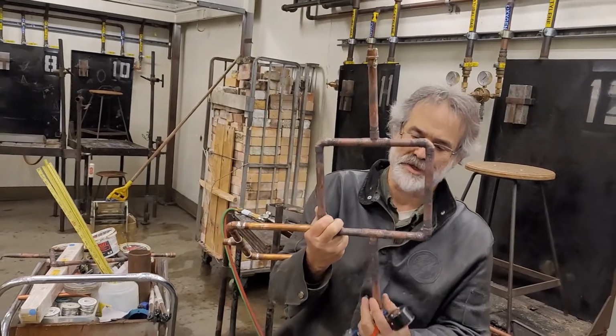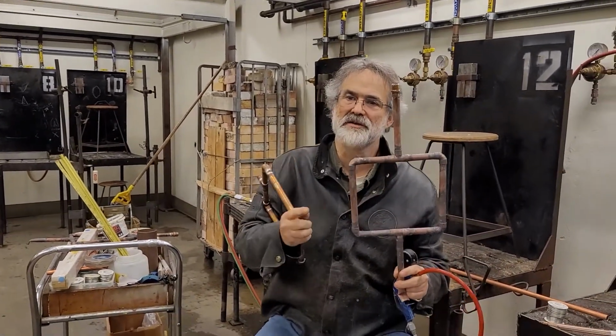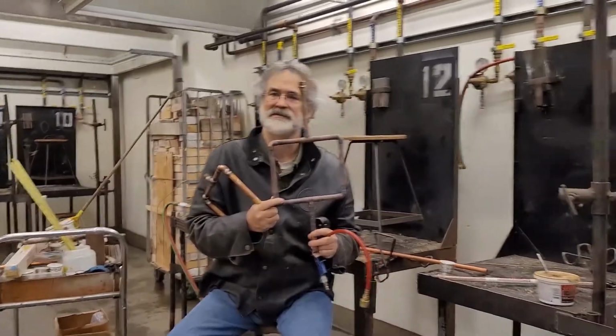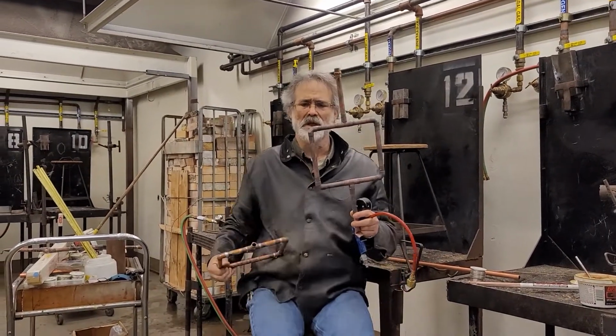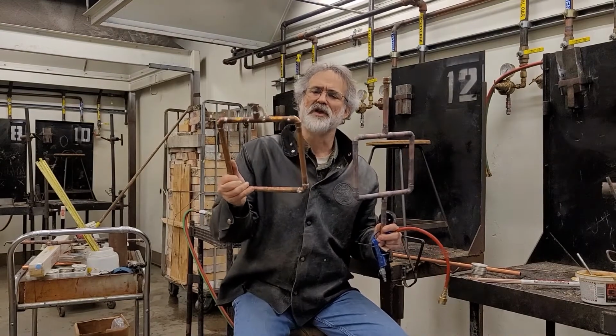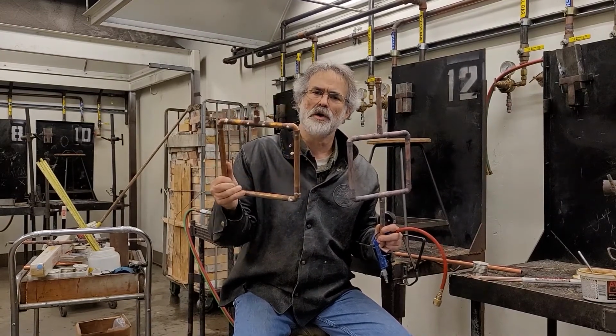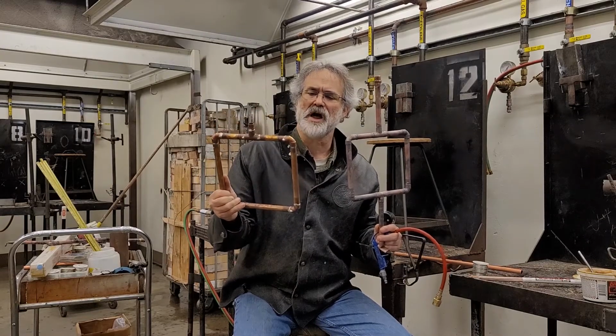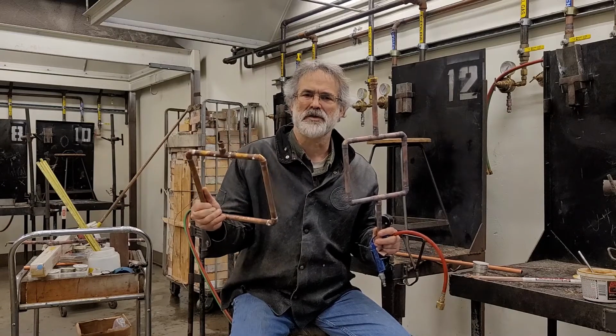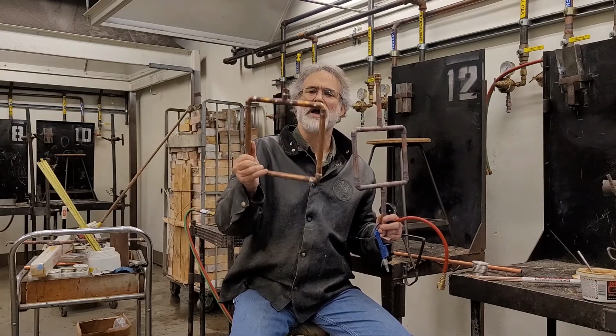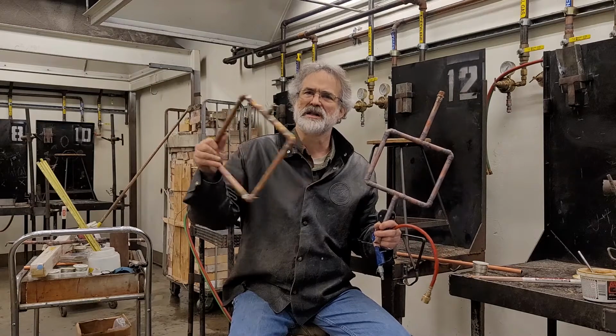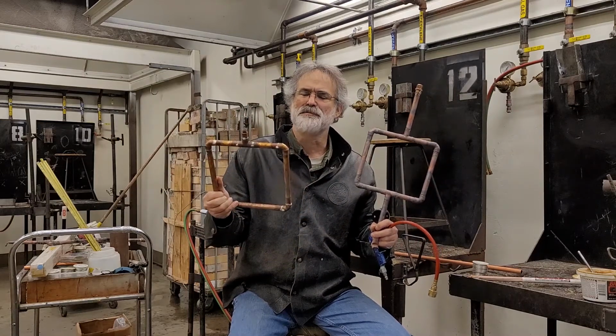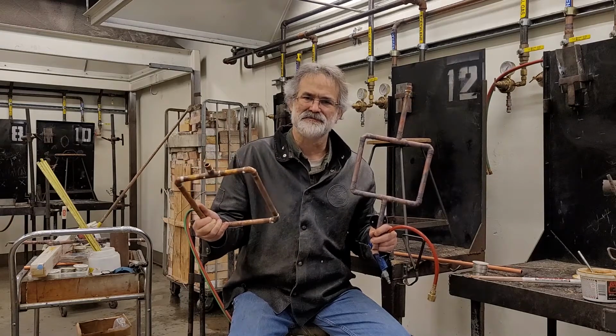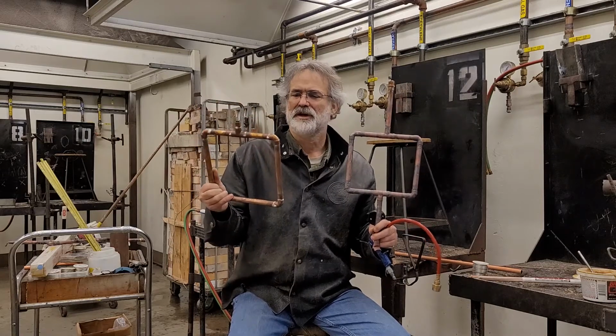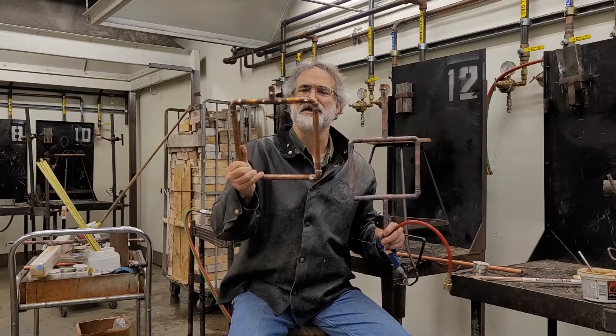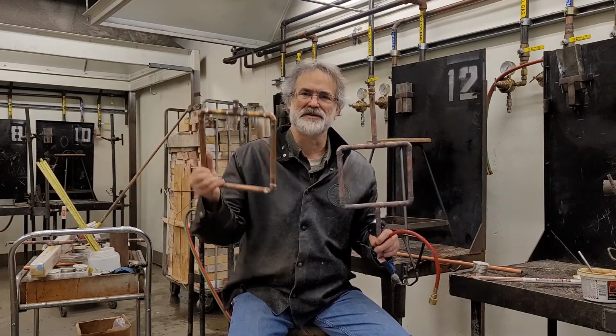Now, the higher temperature rod is much easier to repair because the higher temperature rod doesn't require any flux when we go to weld up. The lower temperature solder requires flux. And a lot of times when there's a hole, it's very difficult to repair because the flux has dried up inside the pipe where the leak is. And so sometimes these pipes here have to be pulled apart, cleaned up real well, right? And then put back together to fix it, which is very difficult to do. And so, especially when we're doing this type of soldering here, we want to get it right the very first time, right?